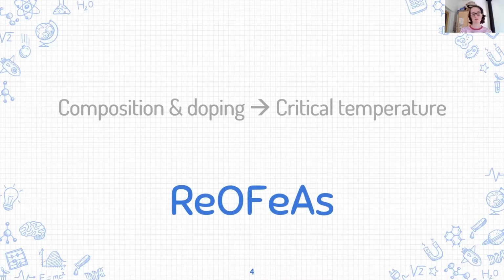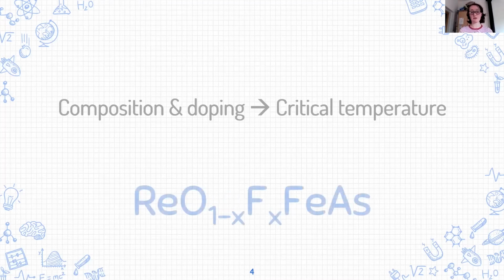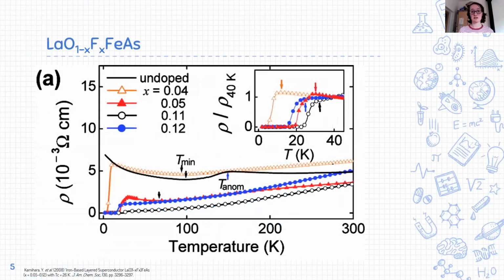So when the field of pnictide superconductors was first starting to emerge, others with the 1111 structure type had been found to be superconducting, but only with critical temperatures like 5 or 7 Kelvin, which is almost useless. And the iron arsenides had been found to be antiferromagnetic, not superconductors at all. But then in 2008, it was discovered that if you dope the rare earth oxygen layer with fluorine, superconductivity will suddenly emerge for these materials. So this is the temperature versus resistivity graph for one of these materials. If you look at the thick black line, that is showing you the undoped compound. And you can see that they've marked a hump with T_N, which represents the point where it changes into an antiferromagnet. But obviously after this point, the resistivity is going up, so it's not a superconductor.